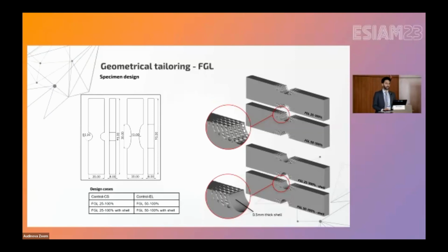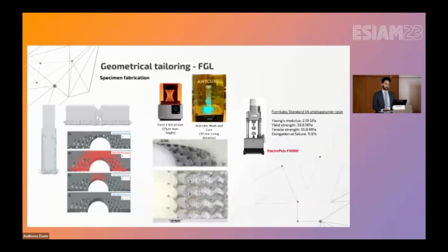Then in order to minimize the boundary condition effect, we added a 0.5 millimeter thick shell around that lattice to make its interaction with the notch bisector line to a minimum level. Okay, so we have 6 cases now. The samples were designed for fabrication. They were fabricated with V4 photopolymer resin using the SLA technique, stereolithography.